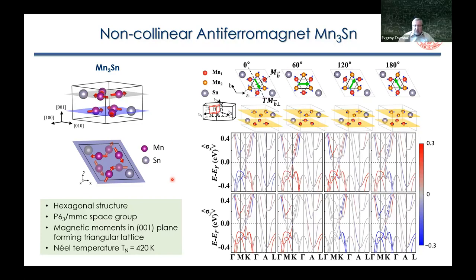Interface is very essential. And as I said, from my perspective as a theorist, I don't know what kind of structure can be used to grow a fully epitaxial tunnel junction. I know that people use MgO as a tunnel barrier, but obviously MgO does not fit the crystal structure, doesn't have a hexagonal structure, and so on. So there is obviously no epitaxy at the interface. And what effect that should produce is hard to say.